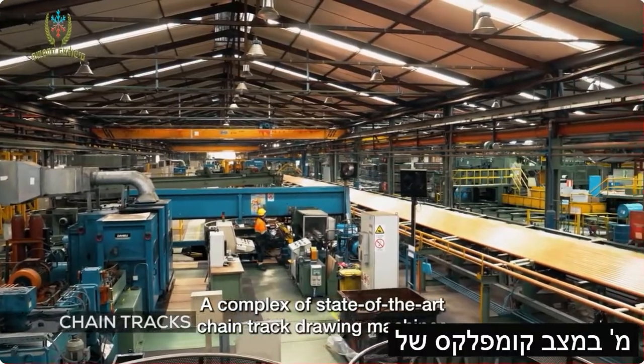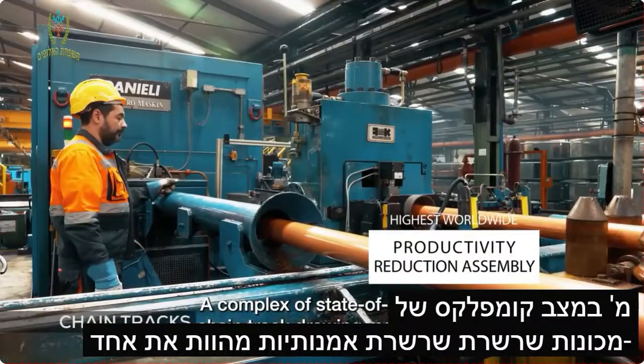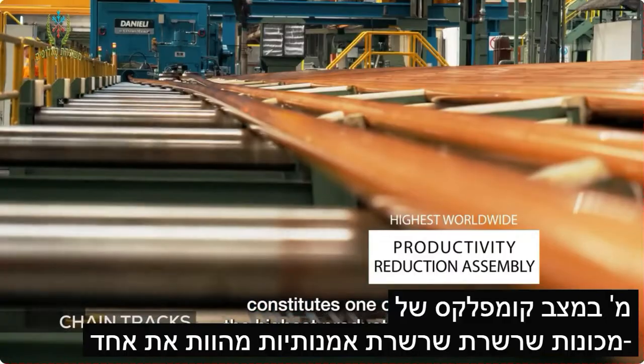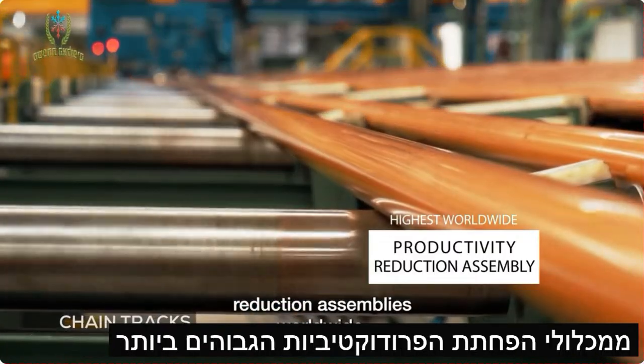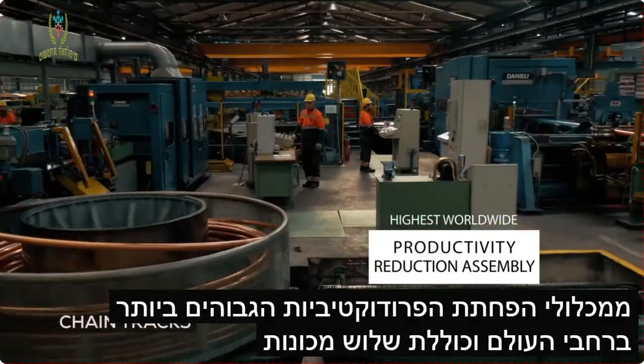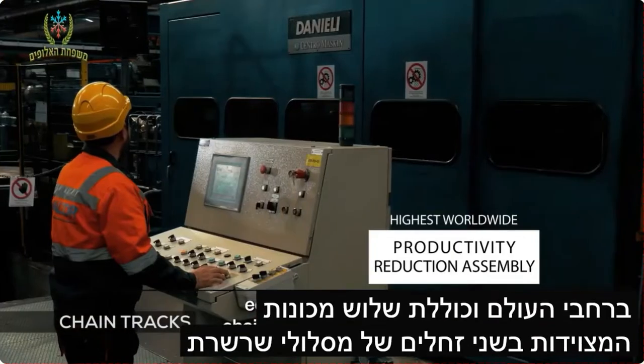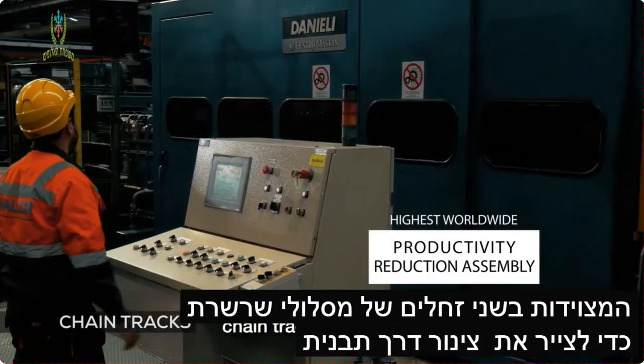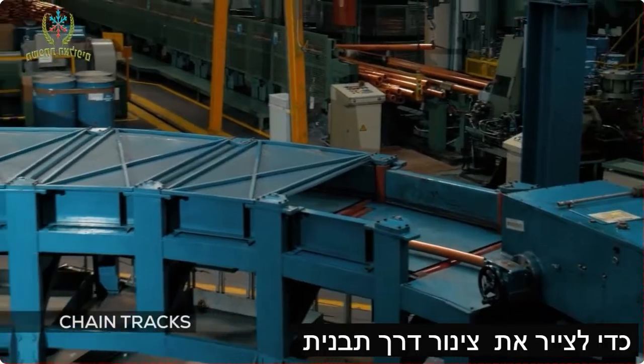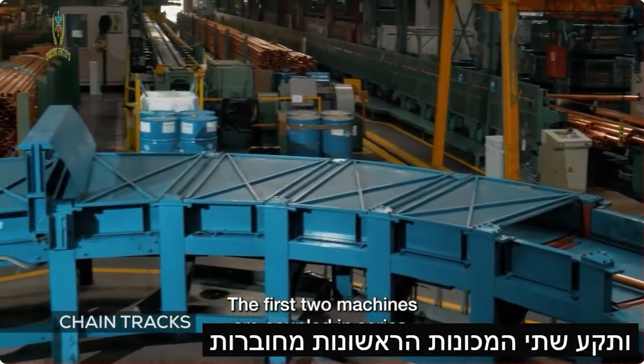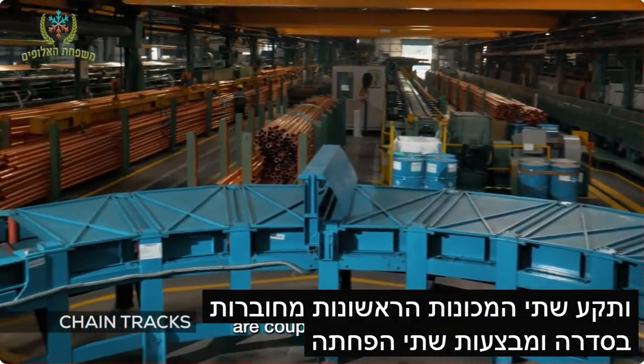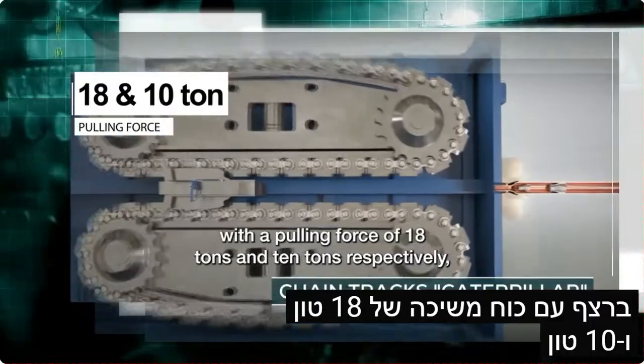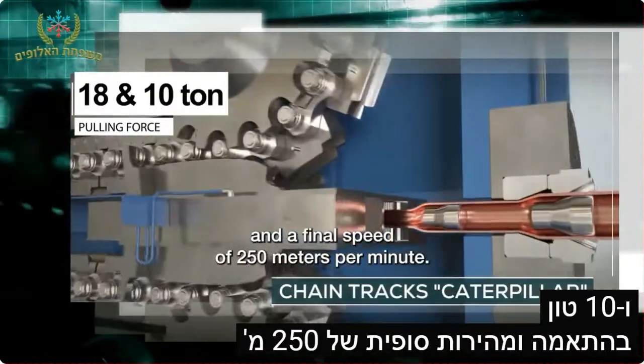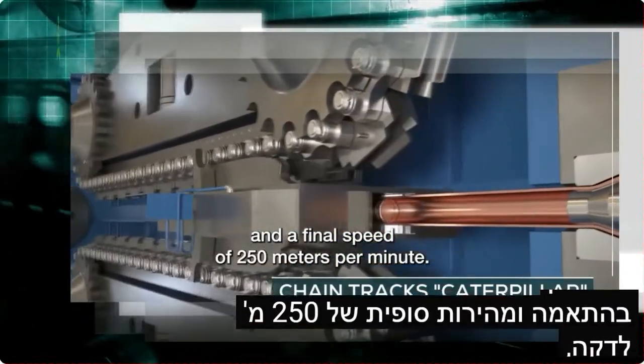A complex of state-of-the-art chain track drawing machines constitutes one of the highest productivity reduction assemblies worldwide. It encompasses 3 machines equipped with 2 chain track caterpillars to draw the tube through a die and plug. The first 2 machines are coupled in series, performing 2 reductions in sequence, with a pulling force of 18 tons and 10 tons respectively, and a final speed of 250 meters per minute.